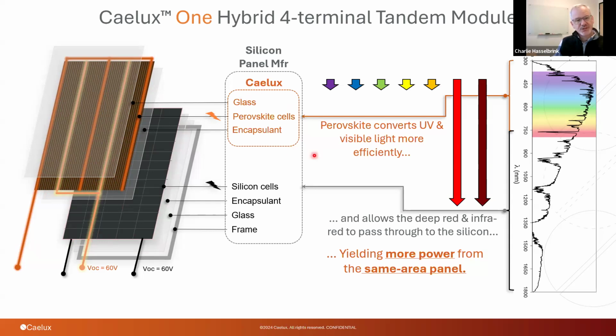The top layer converts the visible portion of the spectrum. We have a 1.56 eV band gap on our product, so we absorb up to about 750 nm. The remainder is picked up by the silicon out to the end of silicon's band gap, and that converts about 8.5 to 9% out of the bottom cell. We are aiming for 17.5% out of this cell. Right now, we're not there yet. I'll show some data about where we're at.